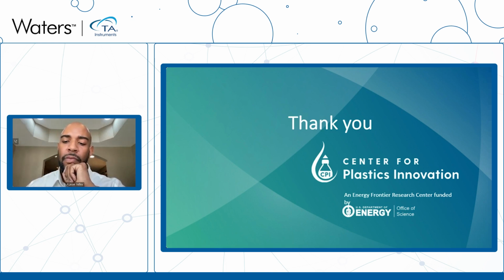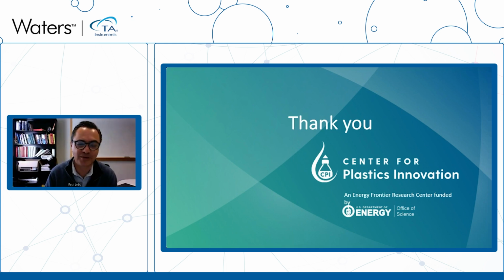We're very concerned about PVC because the chlorine is toxic to our catalyst. Yes. And what I can tell you is that there are ways of pre-processing the polymers so that contaminants of PVC can be removed. We do that by reacting the PVC with bases such as magnesium oxide, and what you produce there is magnesium chloride, and then a stream that is essentially free of chlorine. So there are ways of addressing that, but it requires a pre-processing step.